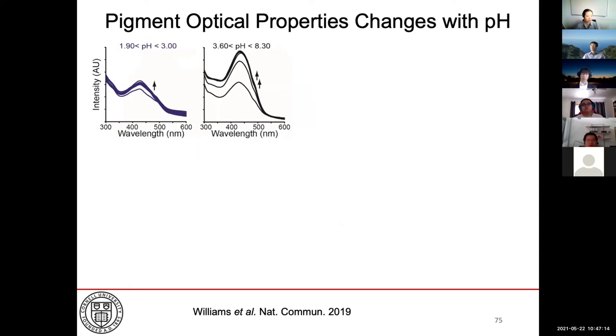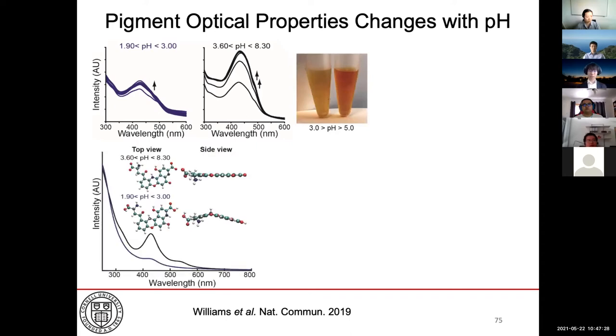Now, by monitoring the absorptive capabilities of synthetic pigment molecules by themselves, we found that above a pH of 3.6, there is a transition in the color. And by calculating the absorption spectra using DFT calculations, this transition was attributed to the fact that at low pH, the protonation of the molecule actually caused it to kink and therefore altered its optical properties.